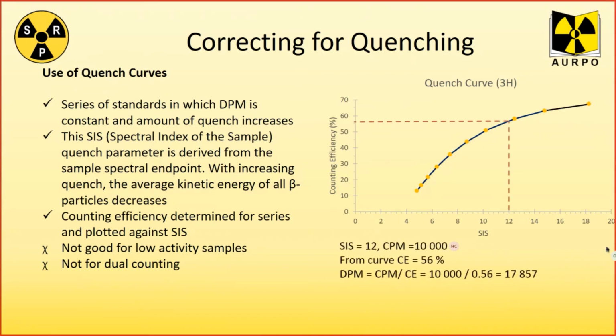You can then work out the counting efficiency of the sample. So here, for example, say we have a SIS value of 12 with a CPM of 10,000. From the curve, we can determine the counting efficiency of 56%. The DPM can then be calculated by dividing the CPM by the counting efficiency to give the actual amount of radioactivity in the sample. However, this quench curve technique isn't good for low activity samples, as SIS may not be accurate, and therefore the calculation can't be either. This method also can't be used for samples containing a mixture of isotopes.